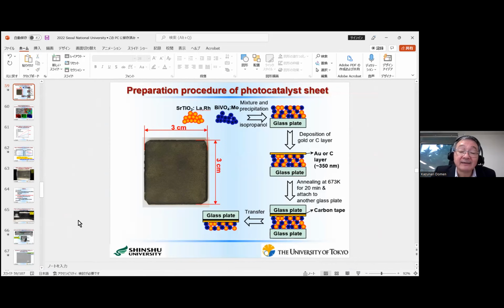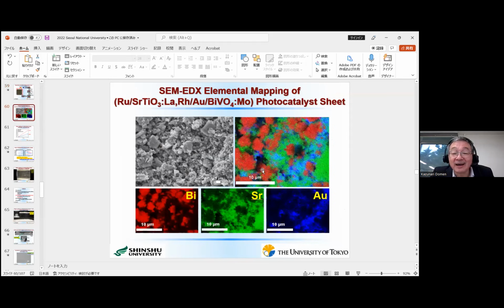I see. What happens if you increase the number of catalysts in the slurry system? Then the probability for colliding with each other improves, certainly. But if we put too much photocatalyst in an aqueous solution, then only a small portion, probably the surface portion of the photocatalyst, can absorb photons. Light. Okay. I should say that although our structure is still very poor, nevertheless the quantum efficiency is better than the suspended system, as shown here. Okay. Very good.